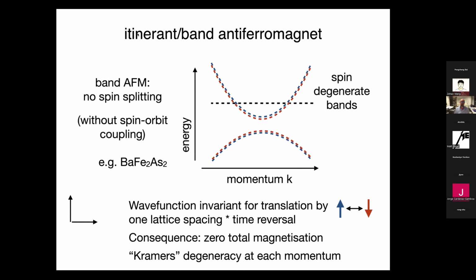So now, if I consider an itinerant or a band antiferromagnet, there is no splitting of the bands, at least in a system without spin orbit coupling, or if I do a calculation and do not consider spin orbit coupling. So I have spin degenerate bands, so the blue and the red band here overlap. I shifted them a little bit so you can see it, but in principle, there is a degeneracy of the bands, and the fact that these bands are degenerate, the up and the down, means that they are equally occupied, and therefore the total magnetization of this system will be 0. The total magnetization of a band antiferromagnet is, of course, also 0.